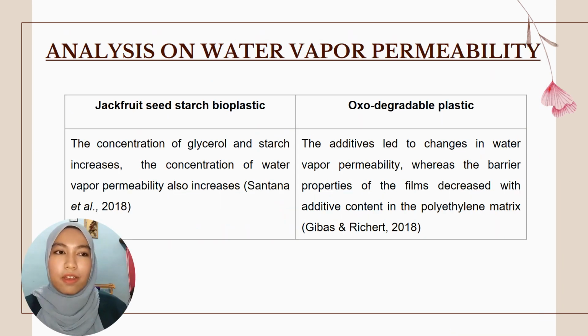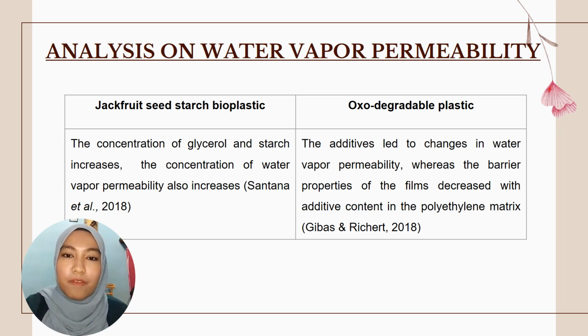For the analysis of water vapor permeability for the jackfruit seed starch bioplastic, according to Santana et al. 2018, as the concentration of glycerol and starch increased, the water vapor permeability also increased. For the oxo-degradable plastic, according to Gibas and Richert 2018, the additive leads to a change in water vapor permeability, where the barrier properties of the film decrease with additive content in the polyethylene matrix.